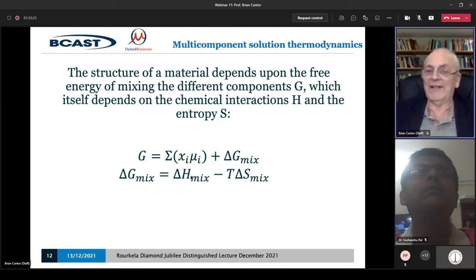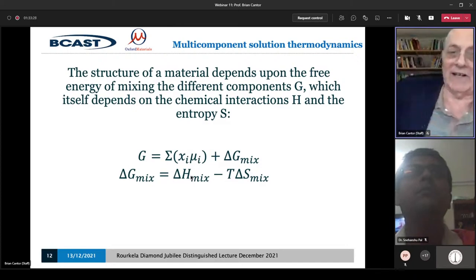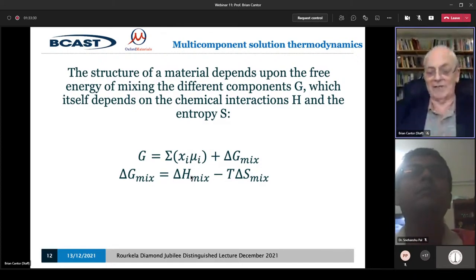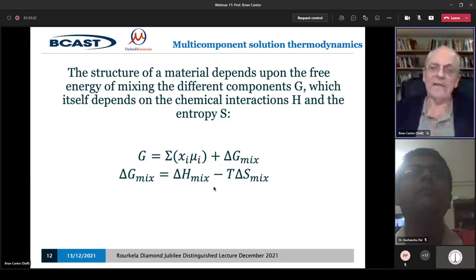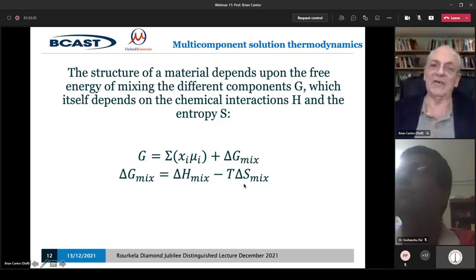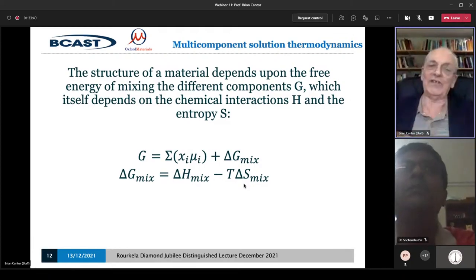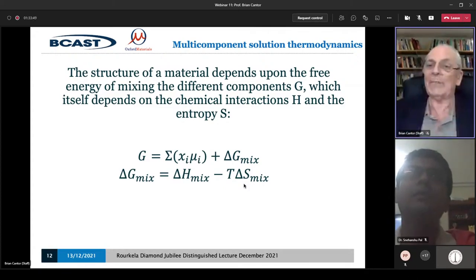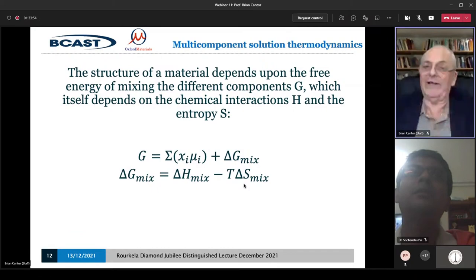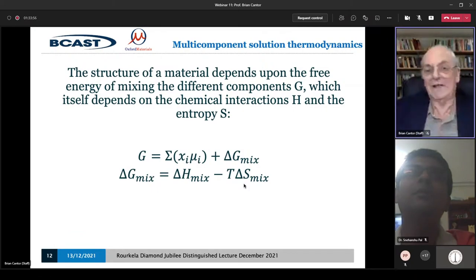It's not especially the multi-component ones, but of course you're quite right. We're relying particularly in the multi-component ones on having them mixed up. The key question is this: does that demixing, as it's called, happen at a sufficiently low temperature that it can take place kinetically? So thermodynamically, if you go to low enough temperatures, instability must appear. But if the temperature's low enough, the atoms can't move, so that it doesn't happen.